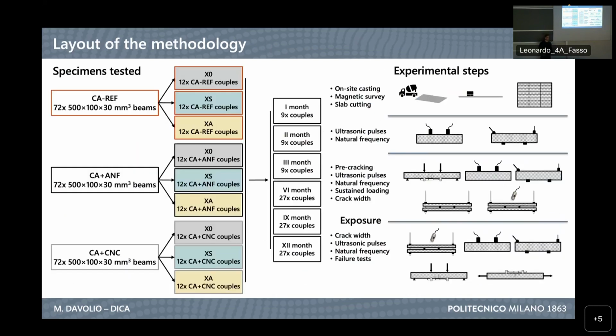And this is the layout of the methodology. I know it's quite a full slide, but we can separate it. On the left side, we see all the specimens we tested. For each material, we had 72 thin beams. We will see a picture of them later. The idea was to expose all of them to the 3 different exposures and test them at different times. For the first 3 months, the testing was carried out on 9 couples globally, and then we took wider time spans of 3 months up to 6, 9, and 12 months, and a higher number of specimens.